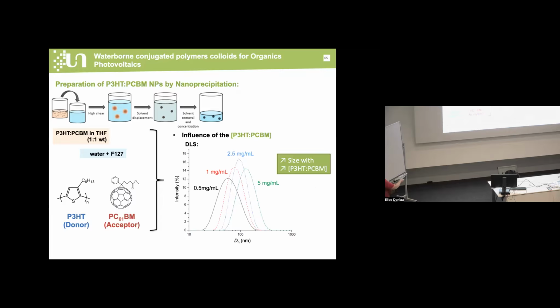So then, as I said, we use P3HT and PCBM in THF in a 1:1 weight fraction of both materials. And we rapidly mix this organic solvent into water. And after the solvent displacement, the polymer precipitates. And after removal, you get the dispersion of the nanoparticles. So we first characterize our nanoparticles using dynamic light scattering. And you can see that the particles are quite